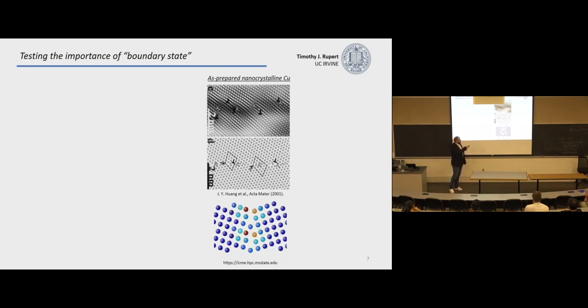And it's compared against, on the bottom here, the sort of perfect, ideal textbook solution of where I would need to have grain boundary dislocations. The main point is that the real material has extra dislocations. So this black dislocation marker is not found in the ideal solution. So the real material has extra disorder in the grain boundary. If you prefer a computational example, you can think about this. If I take 2 crystals, tilt them to whatever misorientation I want, and put them together, that's one way to make a grain boundary. But I can also move those crystals with respect to each other, maybe even add and remove some atoms along that plane to get the lowest energy structure. If you just smash them together in some random orientation, you're going to have a higher energy, more disordered feature than if you find the low energy configuration.